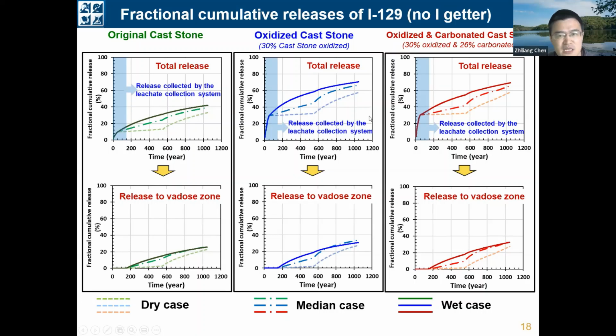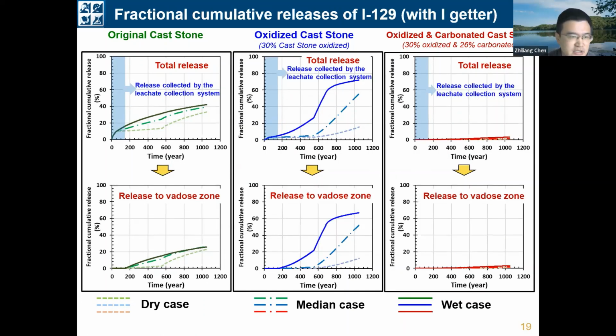And finally, these are the modeling results for the iodine for the system with the iodine getter. The getter in the original capstone barely shows any effect on the stabilization of the iodine, because we didn't observe a reduction of the release from the original capstone. But if we take a look at the results on the right, we can see a reduction of the release. That means the oxidation and carbonation is actually beneficial for iodine stabilization for the system with the getter.